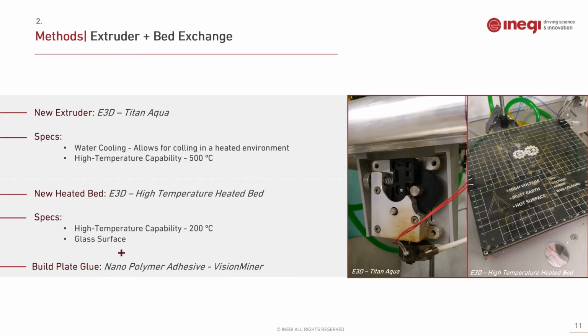For the heated bed, we decided to go with the E3D high temperature heated bed, which has a glass surface and can reach a temperature of 200 Celsius degrees, also meeting the requirements defined. On a side note, for all the tests, we used the nanopolymer adhesive from Vision Miner.